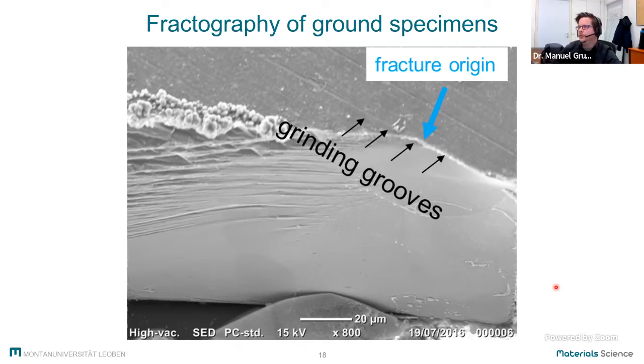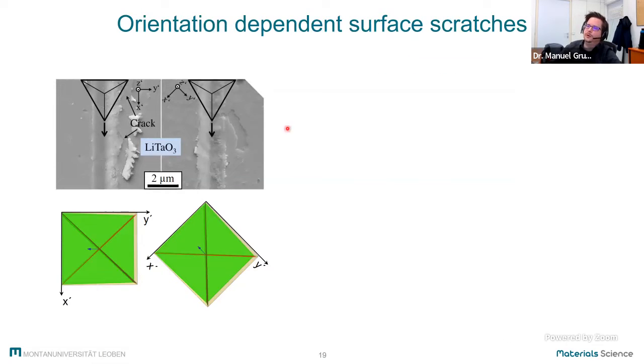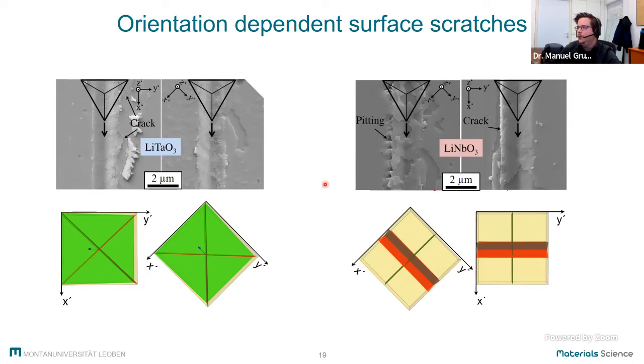However, the grinding process is very complicated. There are a lot of different variables to be considered. So to get a deeper feeling of what's going on in the material, we tried to do some experiments in laboratory conditions. We made scratch tests with a Berkovich indenter with a certain load in a certain direction, and wanted to know how our materials look if we make scratches parallel or at an angle to the cleavage planes